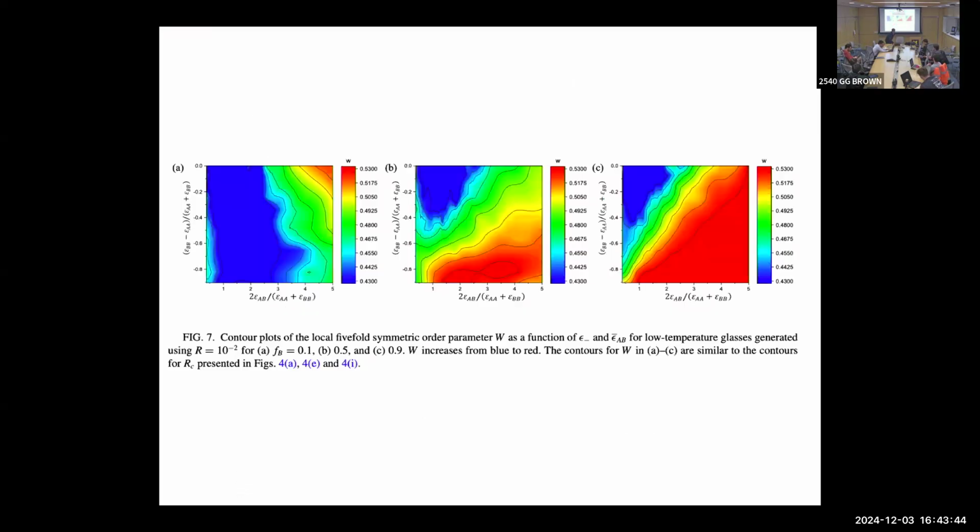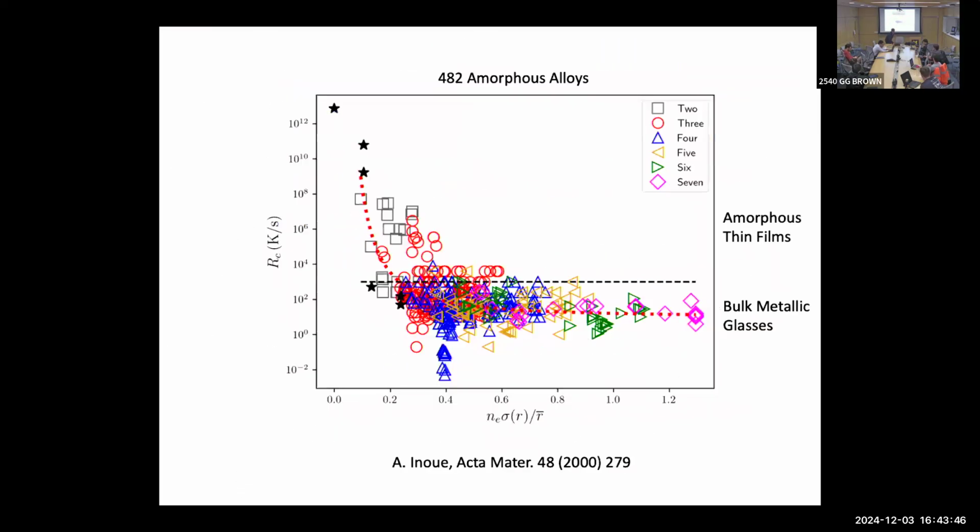Okay, so this data is real data. The pros and cons of real data: it's real data, that's the pro. The con is I have no idea how big the feature space is. Is it 100-dimensional? Is it 4-dimensional? How many features do I need in order to predict the glass formability? That's why Inoue's rules were there. They're like, well, you should have atom sizes that are slightly different. You should have different cohesive energies. You should have a certain heat of mixing. You should have more elements.